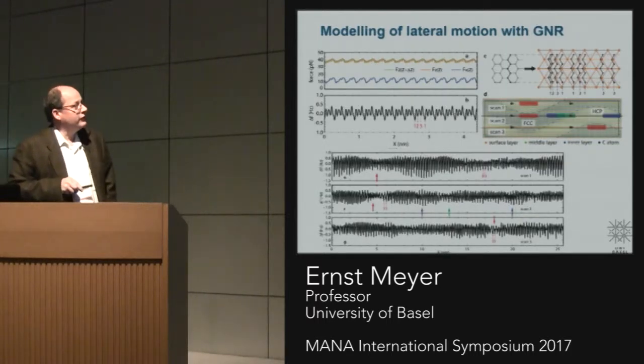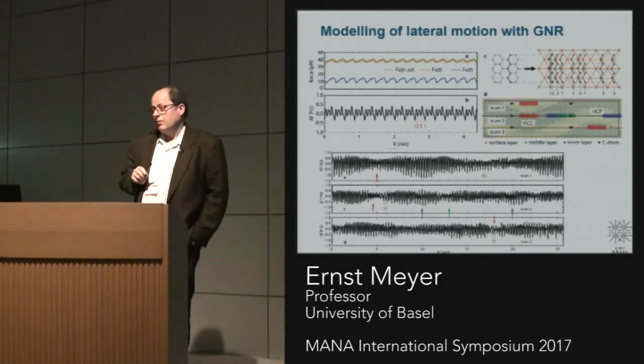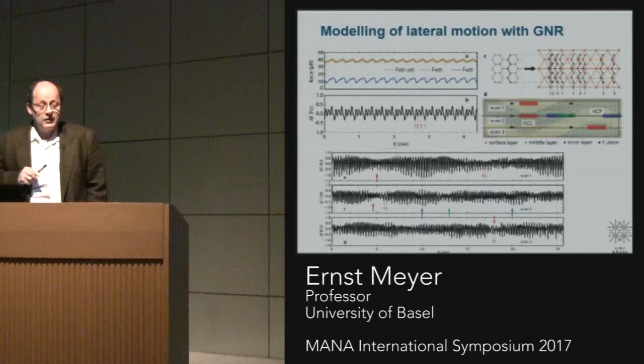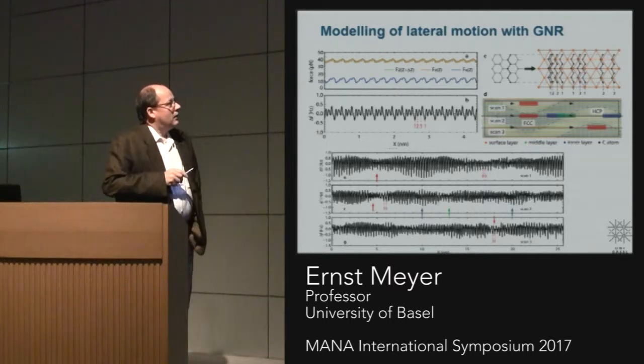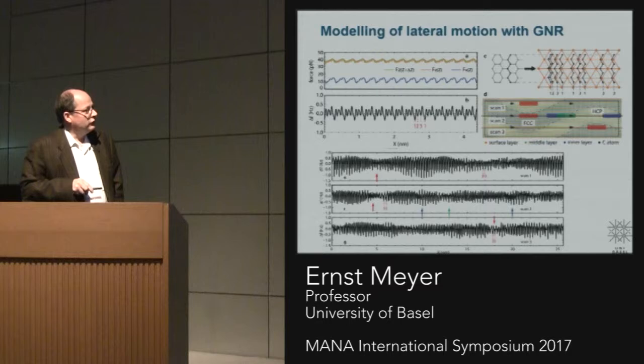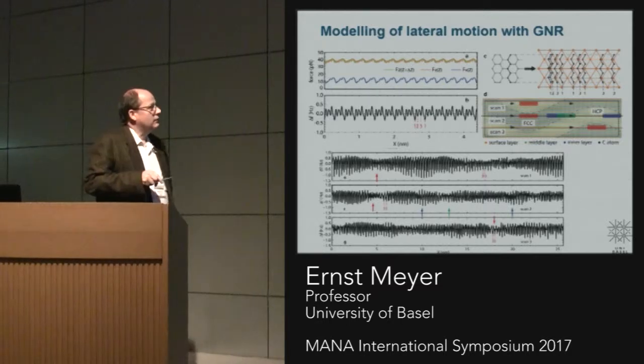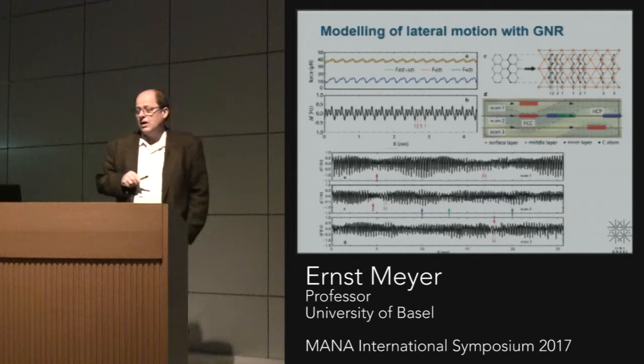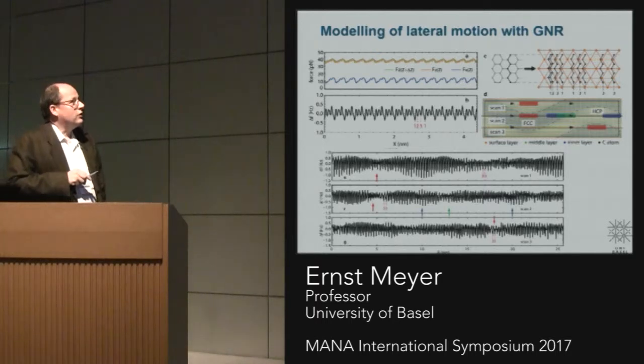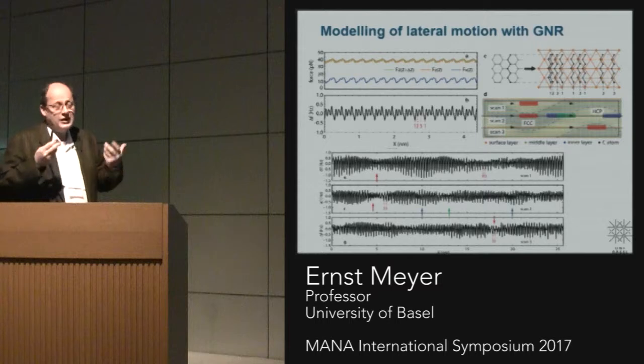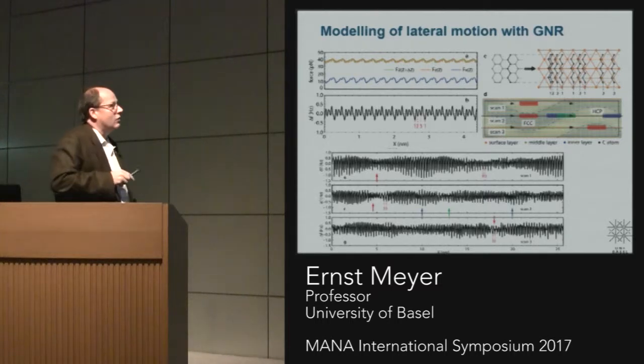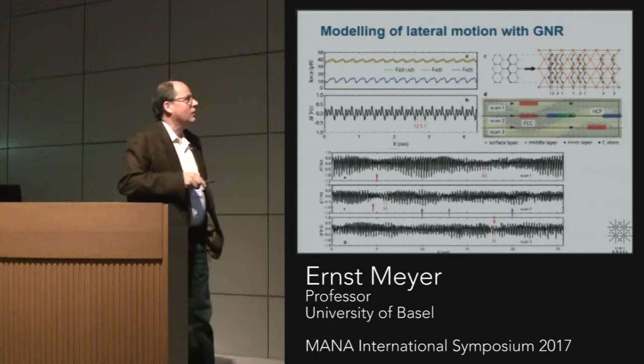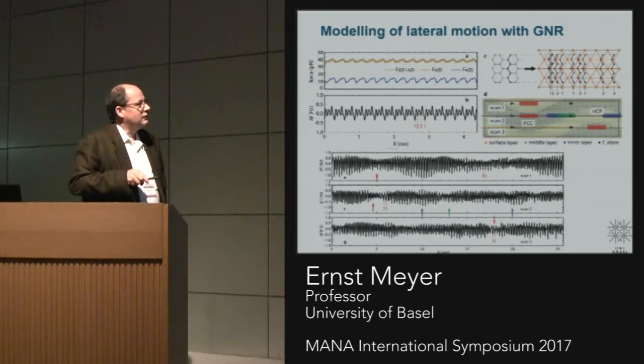So this is now for comparison a molecular dynamics simulation by Andrea Benassi and Daniele Passerone from EMPA. And so they really could reproduce these beating patterns again, and they also reproduce basically this oscillatory behavior. And this can now be understood because of course in MD you can see exactly where you are and which location this ribbon is. And so it shows that if you are on the FCC area here, we get the minimums here, or if you are in the HCP areas also.